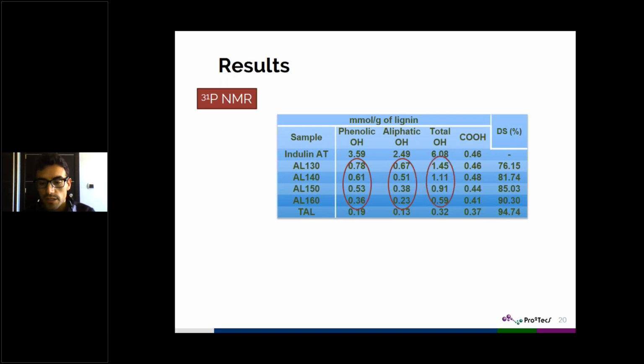So finally, having the same response in the total hydroxyl groups behavior. And finally, we are having a higher degree of substitution as a consequence of that elimination of hydroxyl groups. But it's also worth mentioning that finally, with the traditional acetylated lignin, we obtain the lowest phenolic and aliphatic hydroxyl groups, and finally the higher degree of substitution of these hydroxyl groups.